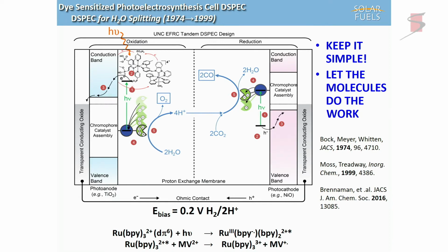So what we showed was you could put it in solution and add a small amount of this pyridinium ion. This is a pyridinium, two of them stuck together. It diffuses up to the excited state, takes an electron away, and the ruthenium goes to the reduced form. The thing about those two taken together with the thought that TiO2 works, you do UV excitation, and that's fine. But that was limiting only because at that point you use a minimal amount of the sun.